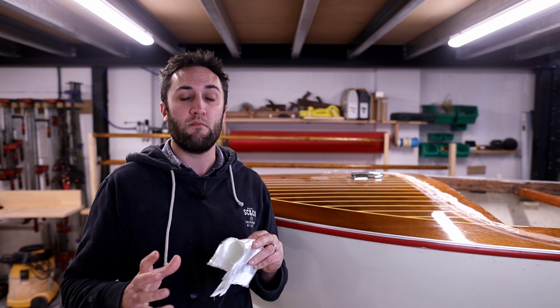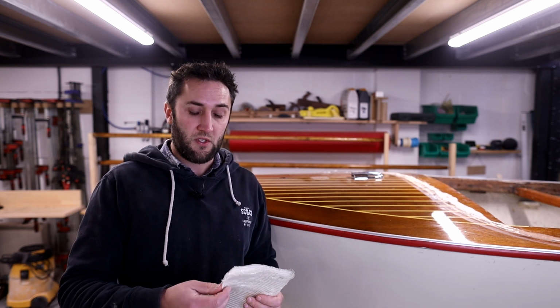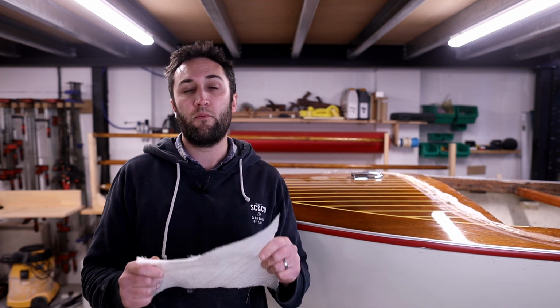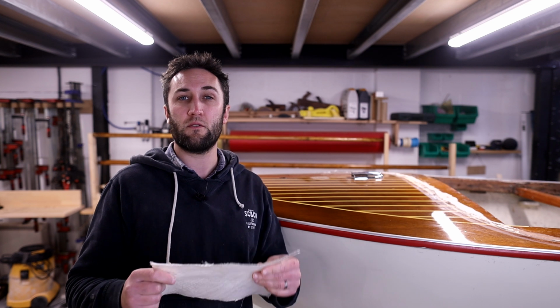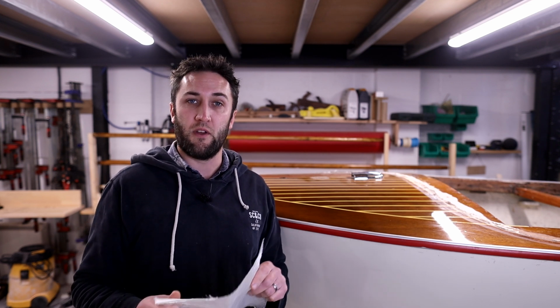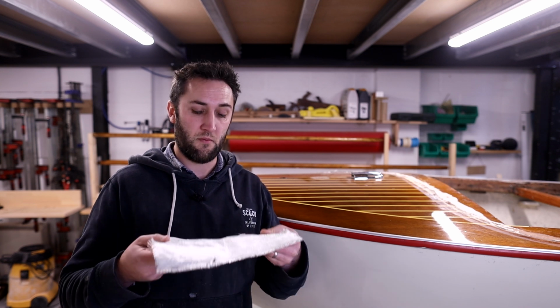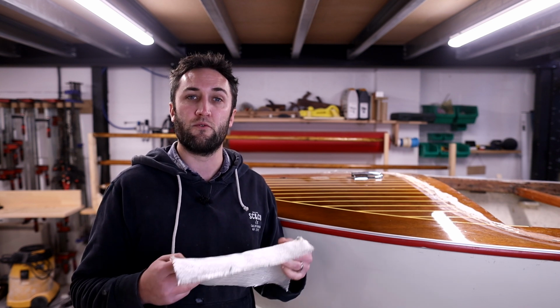You might be wondering to yourself, why have you cut a load of glass out the inside of the boat and then you're putting more back in again? Well, we're actually inducing a very minimal amount of weight within this boat, and we can calculate what that is to quite an accurate degree. So this is 450 gram glass, which is the weight of the glass cloth per square metre. So 1 square metre of this cloth weighs 450 grams. The resin to cloth wet out ratio is 1 to 1. So by the time this is wetted out, it will also take 450 grams worth of resin per square metre.